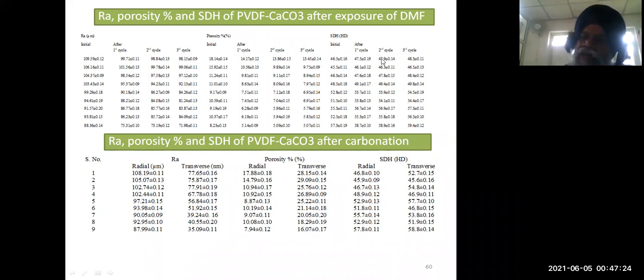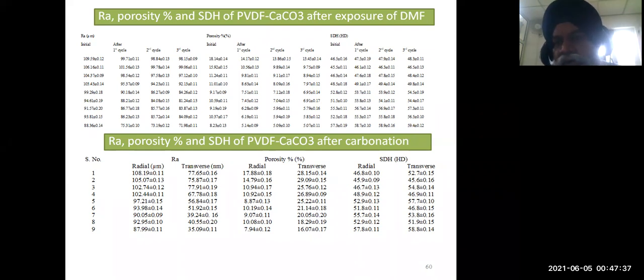Basically, what is happening is the whole surface is made up of peaks and valleys. Once I give an exposure of some chemical, the peak gets dissolved and settles into the valleys, right? So after three consecutive exposures, we are not getting any further good results, right? That is why most of the research papers reported in the past decade have recommended using it up to 3 cycles.